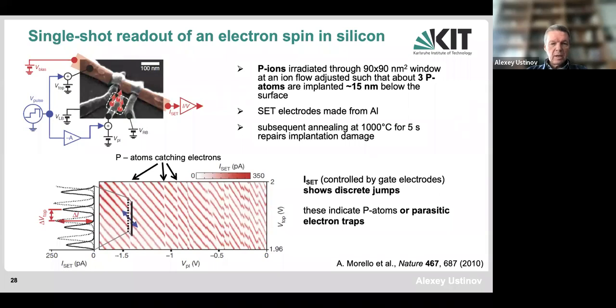So when the phosphorus ions were implanted, they of course mechanically destroy the lattice. They go deep under the surface to a distance of about 15 nanometers, which depends on the beam energy, the acceleration of the beam, which accelerates phosphorus ions. And in order to restore the crystal order around the phosphorus ions, to make the crystal lattice regular and remove the disorder, one has to use thermal annealing. So basically, after the implantation, before depositing the metallic electrodes and forming all this device, the sample was annealed at 1000 degrees Celsius in order to repair the implantation damage. Of course, this is all probabilistic, but by increasing the temperature of the crystal, you make the atoms move, and then they eventually occupy the lowest energy states, which are associated with the periodic lattice.